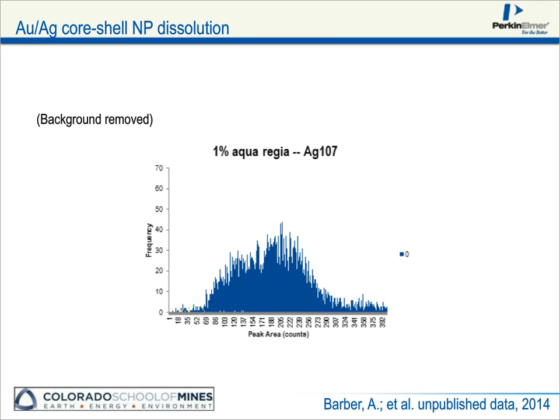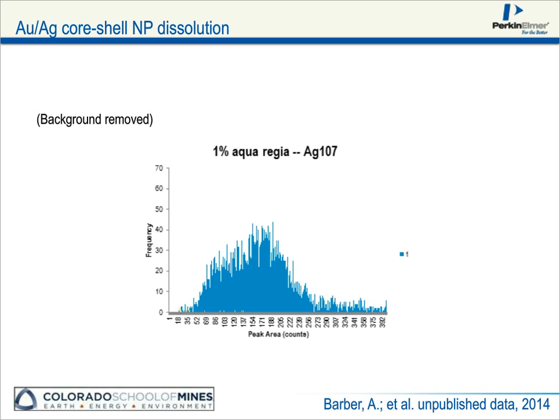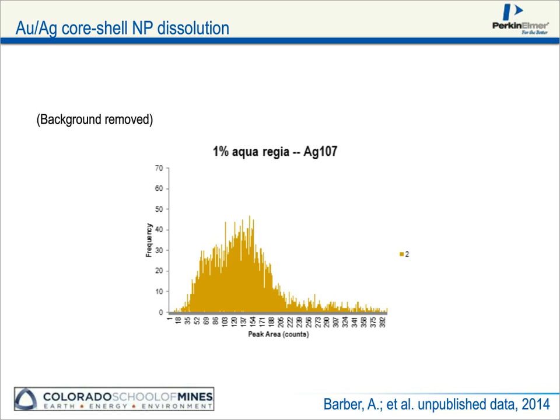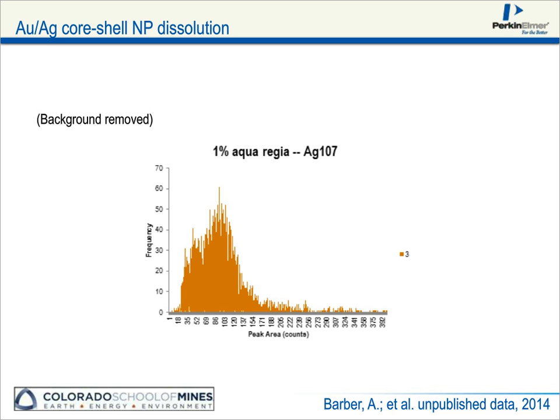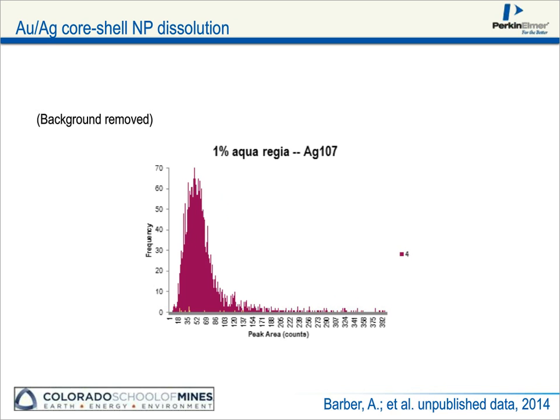As I step through these 30-minute time increments, you can see, as we expected, because the silver is exposed to aqua regia, it is dissolving and the peak is shifting. As we start getting very small, we start to see that the particle signal is actually being lost in the background, which has been subtracted, so you don't see the background. But by 4 hours, there's very few particles left.